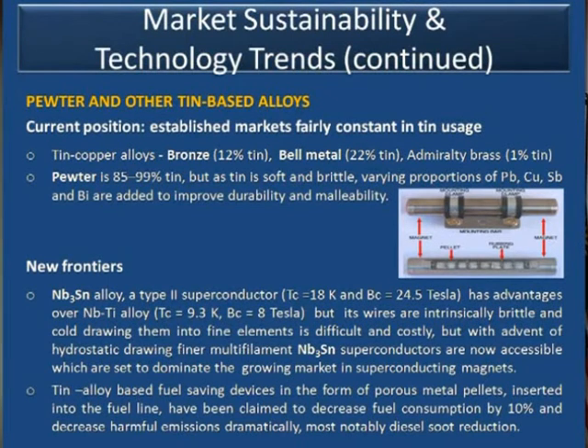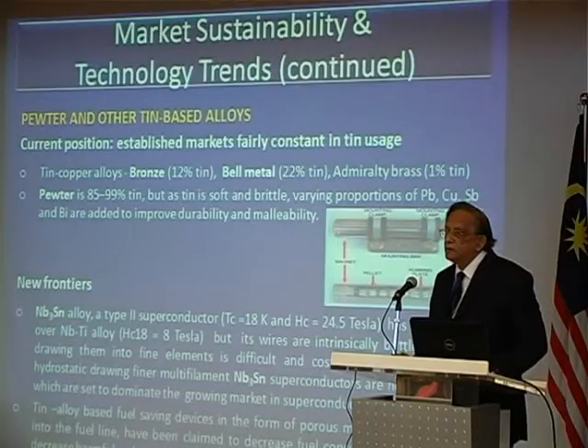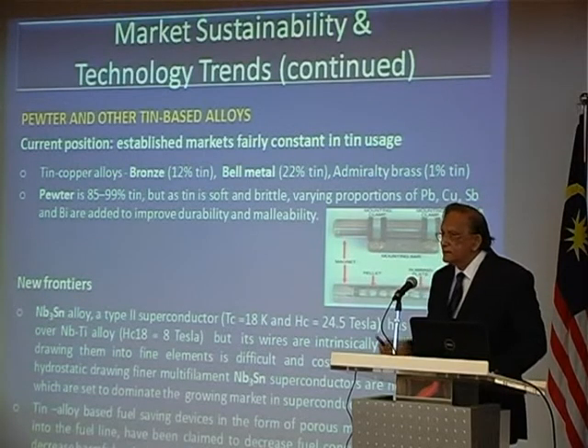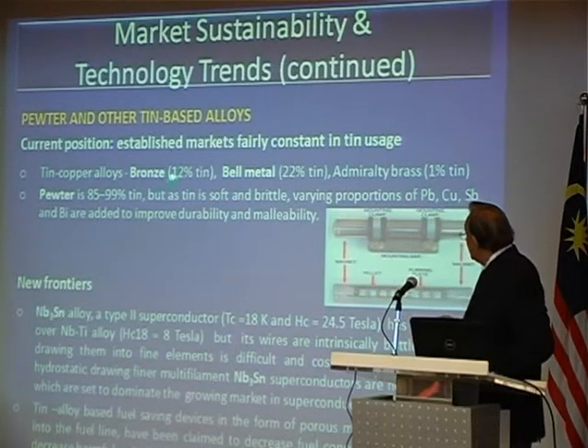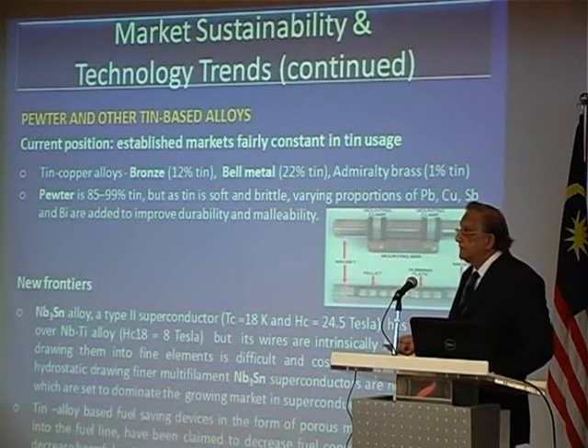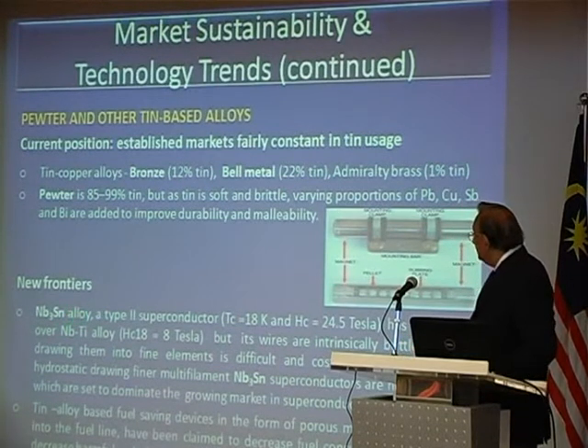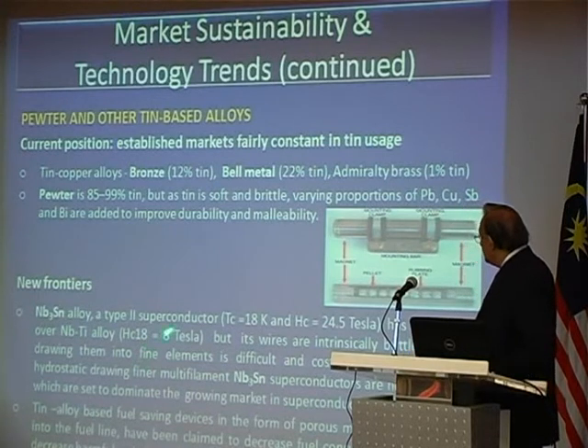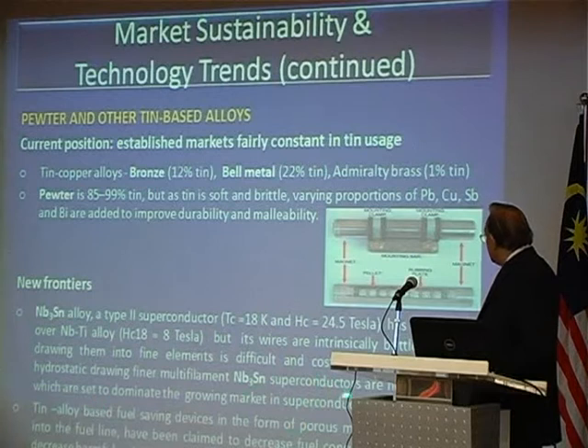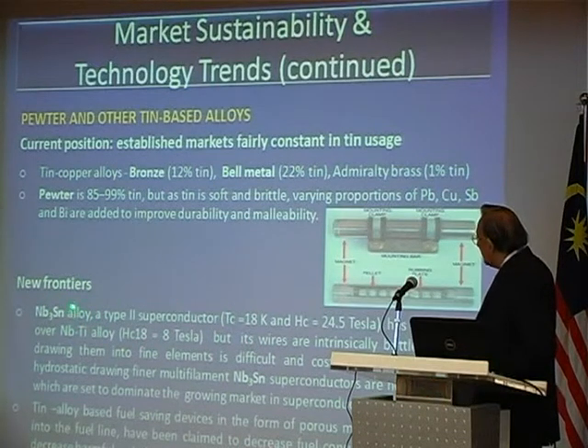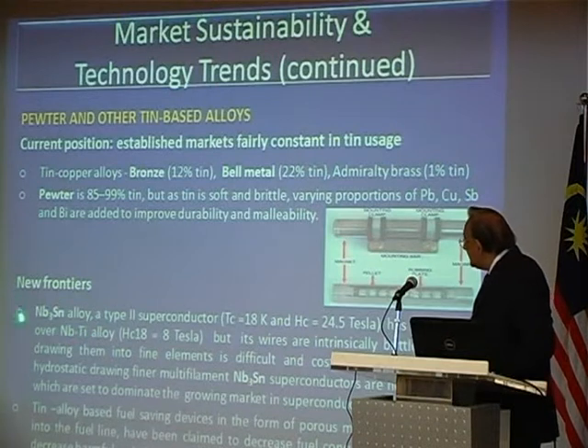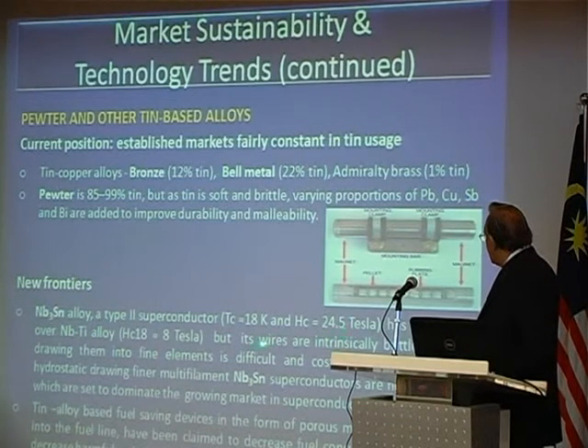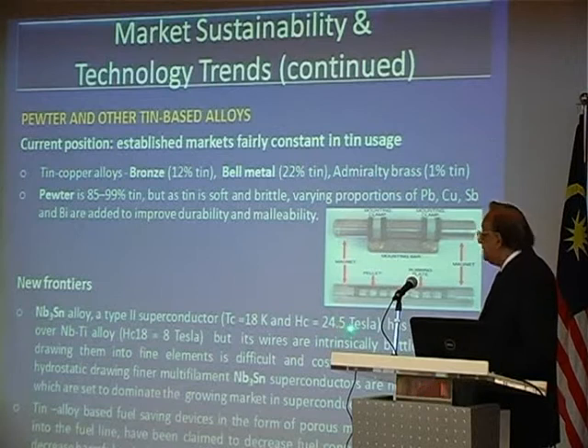Pewter and other tin-based alloys. Now, tin alloys have been known to human beings for thousands of years. In fact, bronze has been known since 3000 BC, and bronze contains 12% tin. There are new frontiers, and that is excitement. This alloy of tin with niobium is a type 2 superconductor, which is used in superconducting magnets. Its nearest competitor, the one that's going to give it a run for its money, is niobium titanium. But it has advantages over niobium titanium because at its critical temperature of 18 K, it has 24.5 Tesla, a higher magnetic field than the niobium titanium alloy, which has only 8 Tesla.